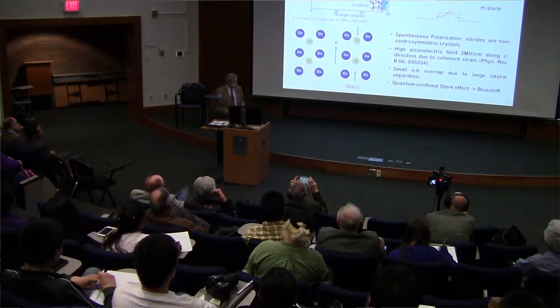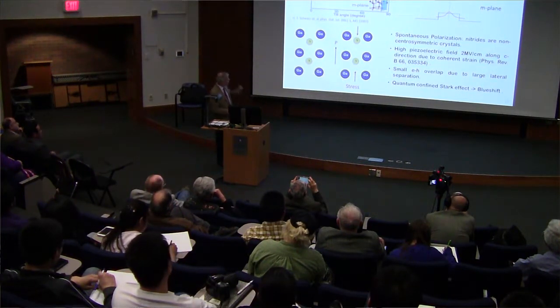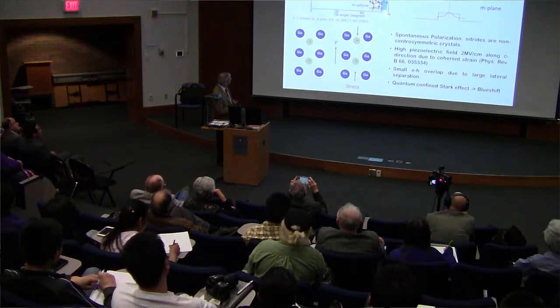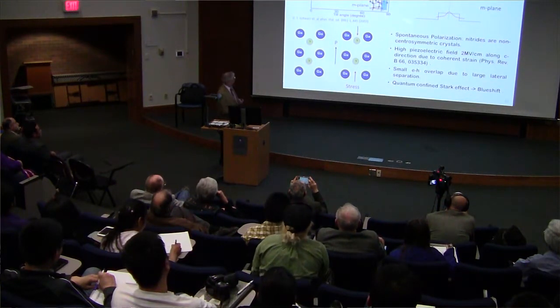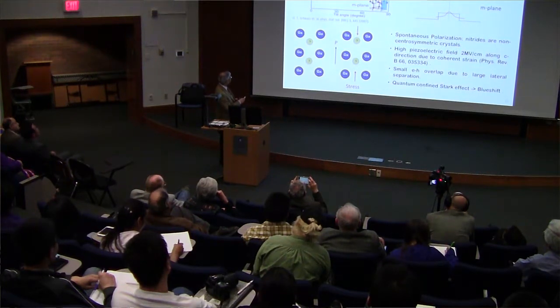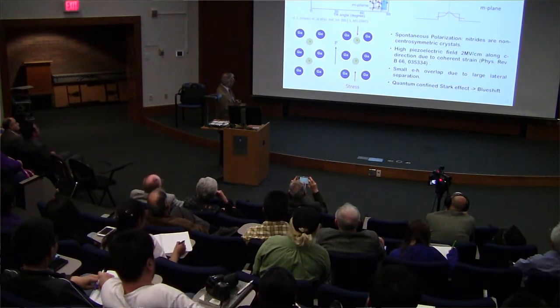Now, one can use other crystallographic planes, like the nonpolar planes, the M plane shown here, or the A plane, where the polarization field is 0 or much smaller, but it's difficult to grow crystals on those planes. In fact, Shuji Nakamura's company has invested a lot in trying to grow LEDs on those planes, but there are materials problems, indium incorporation and so on, which have not been solved. So the favored plane that one grows, all the crystals are in C plane, but you can see there's a large polarization field there. And one has to wrestle with this.